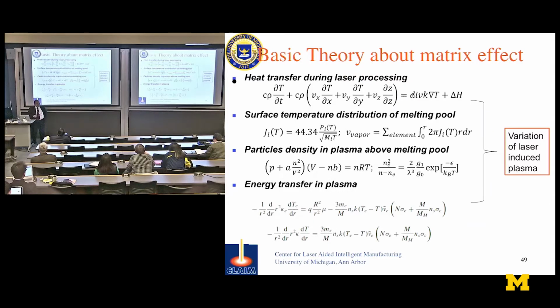And if I can model that, I can essentially get the particle density of the plasma itself over the melting pool. I can get the energy transfer of the plasma. Putting all those, I have a way to calculate what we should expect.